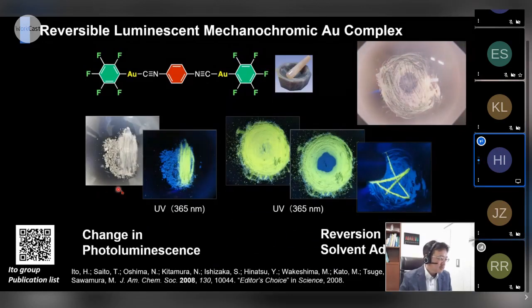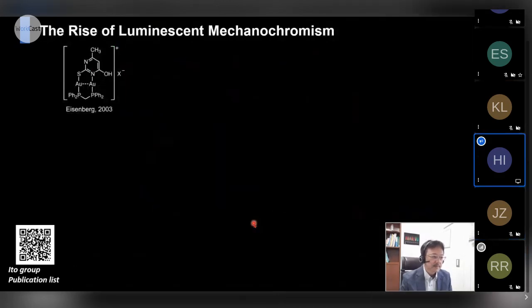And this color change was not observed in room light. Only a color change was observed under UV light illumination, like blue to yellow. And this color change was reverted to the original blue color by adding some organic solvent. And this is a luminescent mechanochromism.